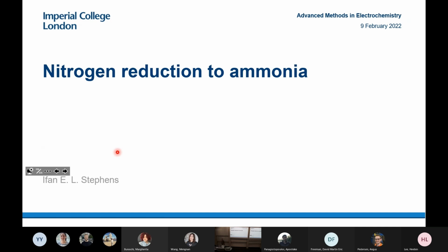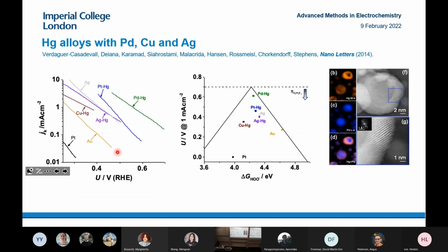I have a question. When you mentioned all these nitrogen carbons, when you look at the reports in literature, it doesn't really seem to be a correlation between the metal center and the selectivity to hydrogen peroxide. So you're asking why is there no correlation between the metal center and activity? There could be a number of reasons for that. One could be the DFT got it wrong. The other thing to bear in mind, which I didn't explain now, is that it depends a lot on the mesoscopic structure as well.